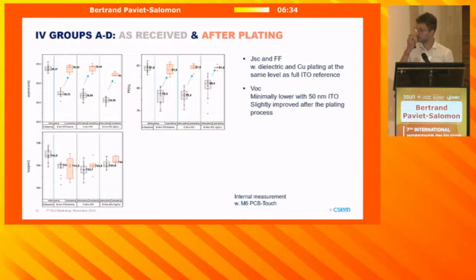VOC-wise, one interesting point to mention is that we observe that already in the as-received state, there is a 1 to 2 millivolt VOC penalty for the thin ITO. We ascribe that to a non-optimal alignment of the band with those thin ITO. But what is interesting to notice is that this VOC difference is not made bigger after the plating, and sometimes is even partly compensated by the process.